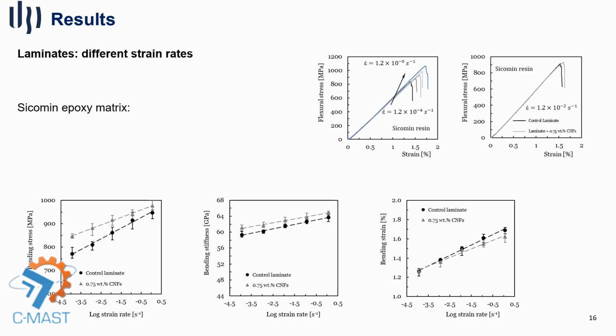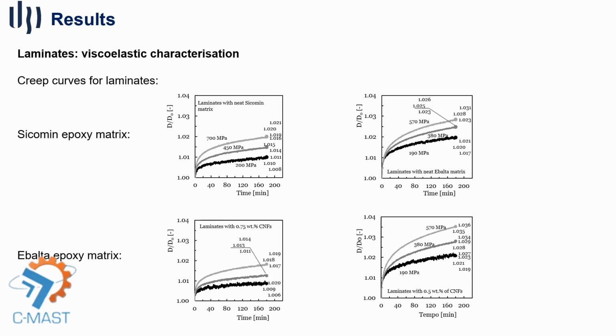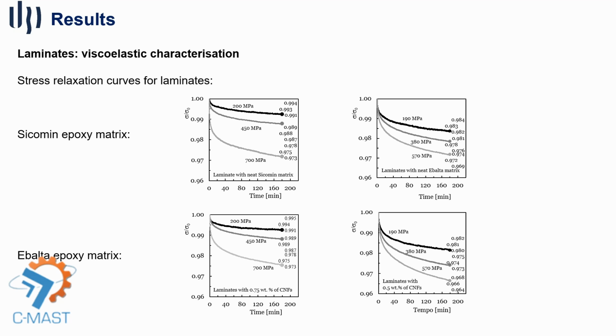In terms of strain rate, this depends directly on the strain rate applied to both control and nano-enhanced laminates. The nano-enhanced laminates improved the properties in terms of stress and stiffness. In these graphs, we can compare the creep behavior of the control and carbon nanofiber laminates for 3 hours of tests at various applied stresses. It is similar for stress relaxation tests, for 3-hour tests and various applied deformations.